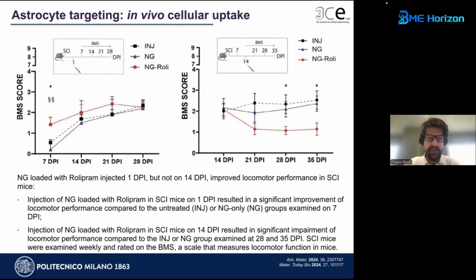The difference between the graph on the left and the graph on the right is that on the left you have the nanogel injection 1 day post-injury, while on the right, 14 days post-injury. And you can see that you have an amelioration only at the beginning, only if you inject the nanoparticle in the first step. But we have to be honest that we don't expect a long-lasting effect because, as you know, we are working with the primary event, and then we need to add something that can rebuild the damaged tissue.